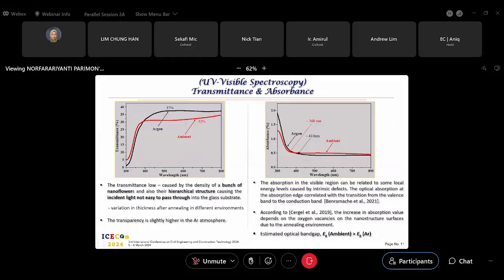Okay, for the optical properties, we measure the transmittance and absorbance of the samples. From the transmittance plotting, we can see the argon annealed sample has higher transmittance than the ambient atmosphere, which are 37% and 32%. The transparency is slightly higher in the argon atmosphere.